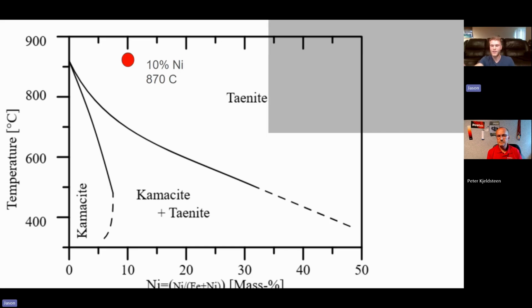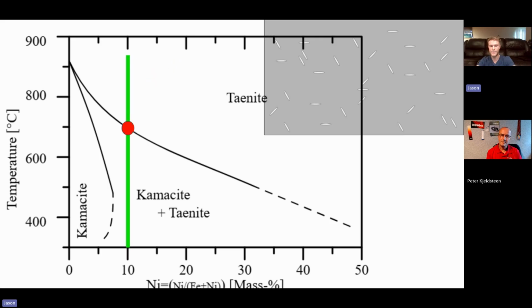Oh, sorry. This is what that would look like. If we took a slice of that meteorite, this is what it would look like, right? Just one phase, homogeneous, all taenite. But 50 million years later, let's cool down along this line. We're going to remain the same composition, 10% nickel. 50 million years later, we start to form kamacite. Remember, because as we cool, there's less energy in the lattice for taenite to accommodate all that iron. And so that iron will precipitate out as kamacite to relieve the stress on the taenite.